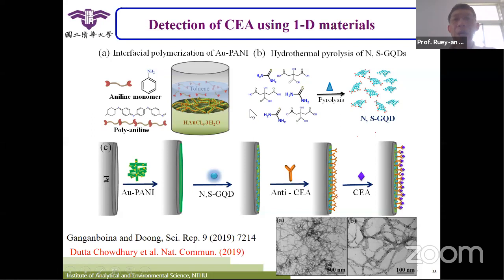We put the gold on the surface actually, so you can see the gold here, and then put the NSGQD here. So that's how we immobilize these materials on the surface of the electrode, platinum and some others. When we enlarge the image, we can see that this one is the PANI, quite good, one-dimensional. When you put the gold on the surface, you always see some spots here. These spots are the gold nanoparticles. And then we use this to put the NSGQD and the anti-CEA antibody on it to detect the CEA.